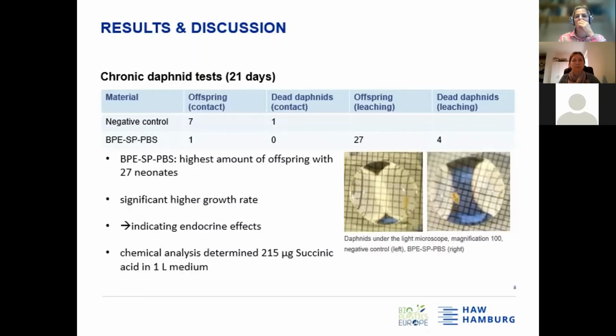So here are the results for the chronic tests of the PBS material, and as you can see, we had a high amount of offspring with 27 neonates during the test period. And also we observed a significantly higher growth rate of the daphnids during the test. So the adult daphnids grew stronger than the daphnids from the negative control. And this indicated endocrine effects.